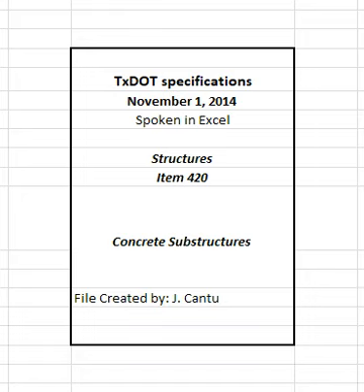Article 7.12. Placing concrete in hot weather. Keep the concrete at or below the maximum temperature at time of placement as specified in Section 420.4.7.1, Placing temperature. Sprinkle and shade aggregate stockpiles or use ice, liquid nitrogen systems, or other approved methods as necessary to control the concrete temperature. Article 7.13. Placing concrete in water.